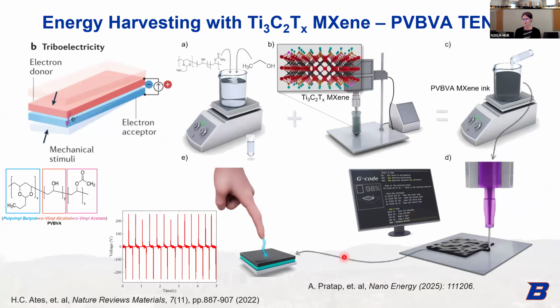That's the energy storage side. Turns out MXenes can actually help enhance energy harvesting as well. And we turn to triboelectric nanogenerators, which is basically a way to convert mechanical energy to electrical energy through contact electrification, right? One material comes in contact with the electron acceptor. The charge has to redistribute when these two come into contact, and eventually it'll come to equilibrium. And as you take them out of contact, that charge will redistribute again. That gives you these characteristics of voltage versus time.